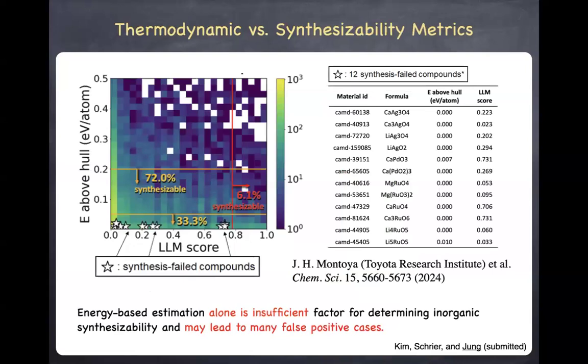And one thing I also wanted to highlight was this comparison between thermodynamics and synthesizability metrics. On the right, you have about 12 compounds that were screened thermodynamically by Toyota Research Institute. They used these thermodynamic estimations to identify some synthesizable compounds so that they could try them experimentally. You can see that all of these compounds have energy above hull of zero or very close to zero, meaning that they are thermodynamically basically stable. They tried to synthesize all of them, and none of them were synthesized. So they failed to synthesize all of them, although they were predicted to be synthesizable according to thermodynamics.